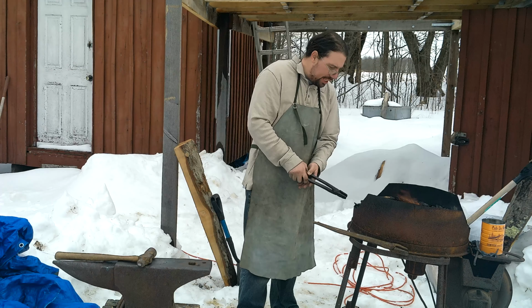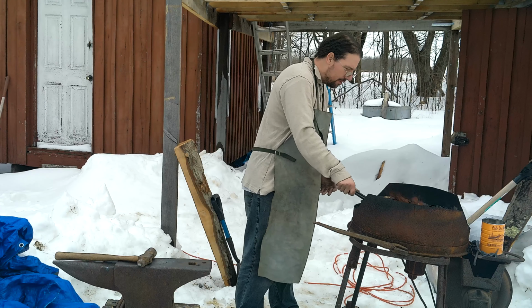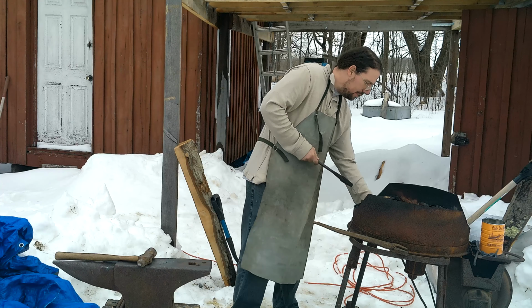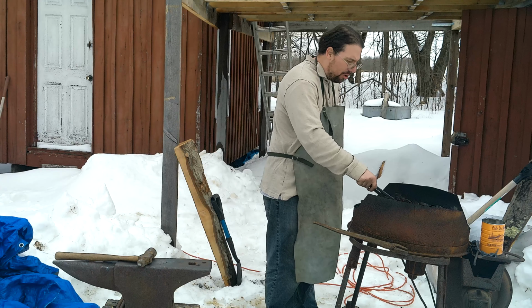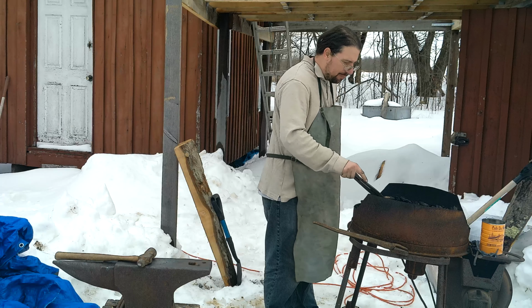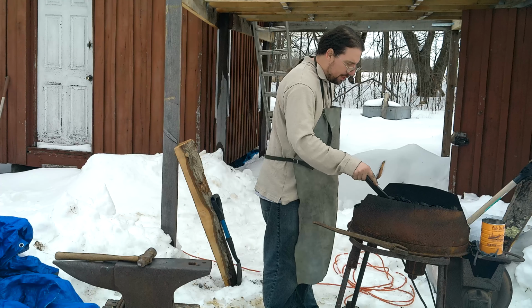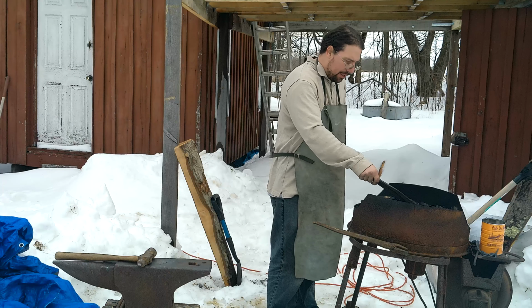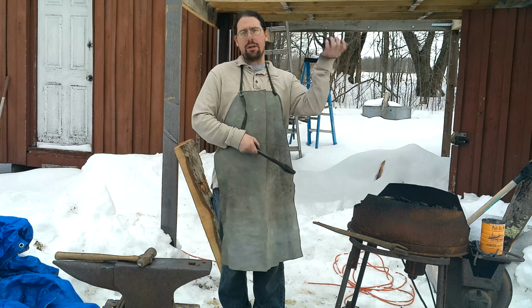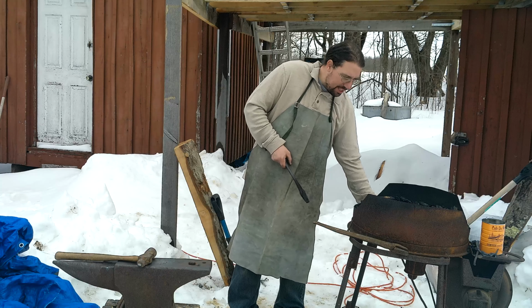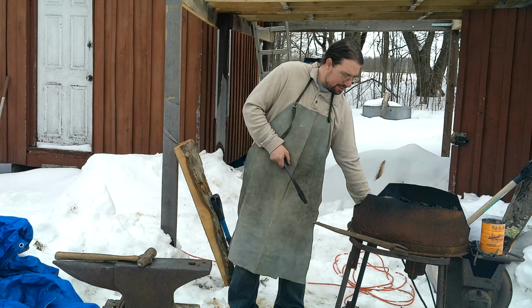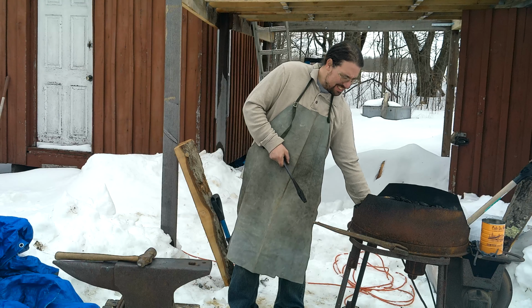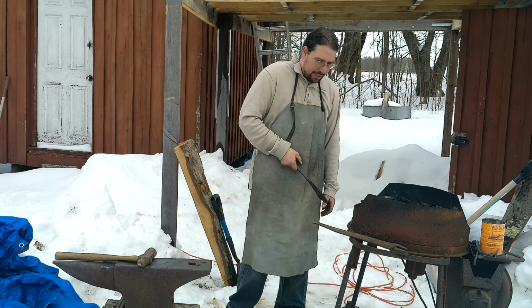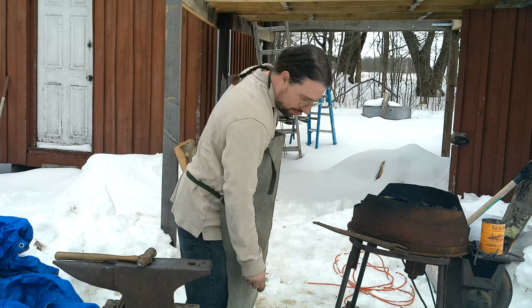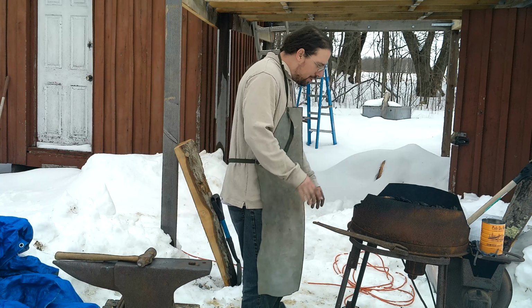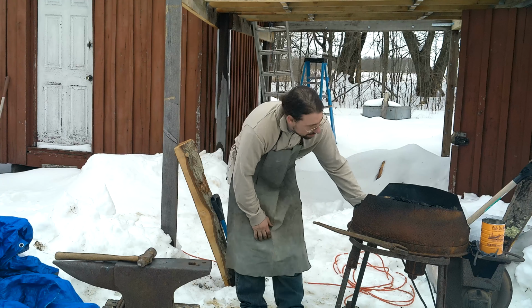Now we're going to go for the heat treat. To do this, I need to get the whole thing to an even temperature, and I can't have the blast on to do it. I'm going to need to bury too much of it, and if I have the blast on, I'm going to burn it. So I'm just going to keep the coals at the surface at the temperature I want. Pulse the air a little bit. Cool off my tongs. Pulse the air a little bit just to keep it at temperature, but not get it crazy hot, or you will ruin it.